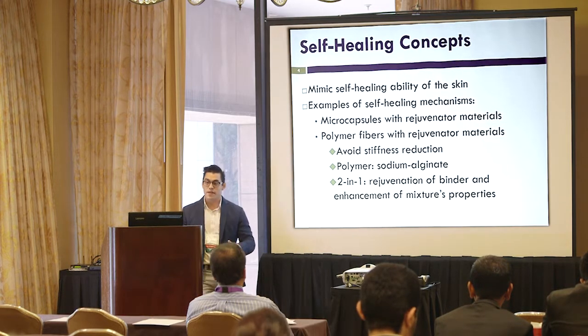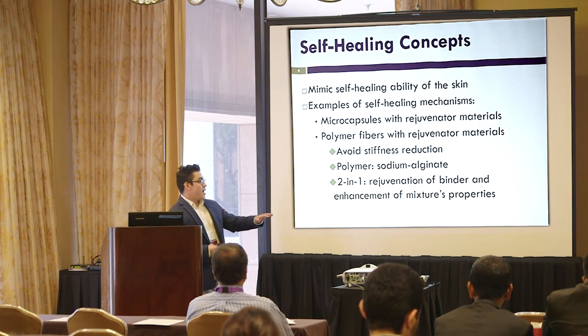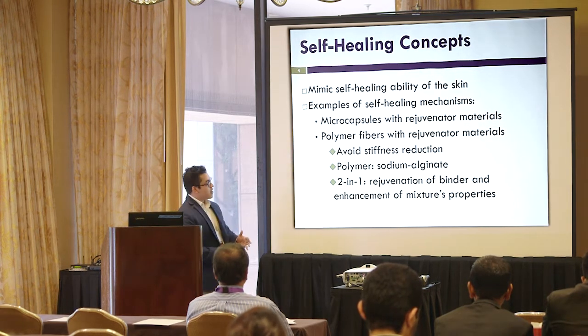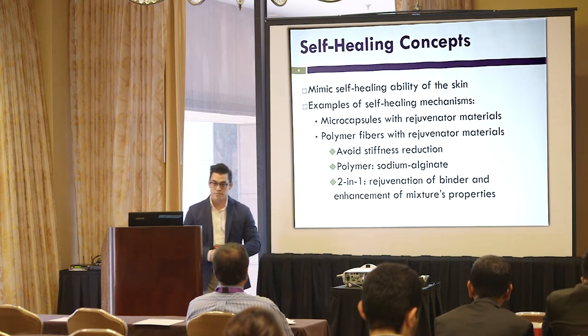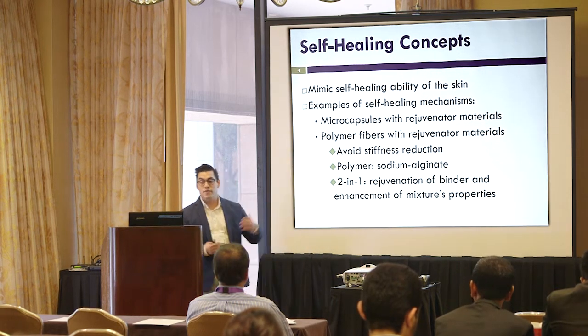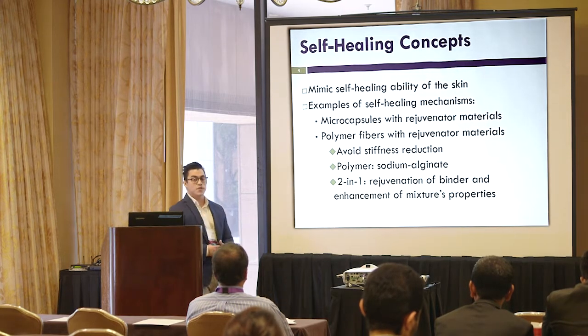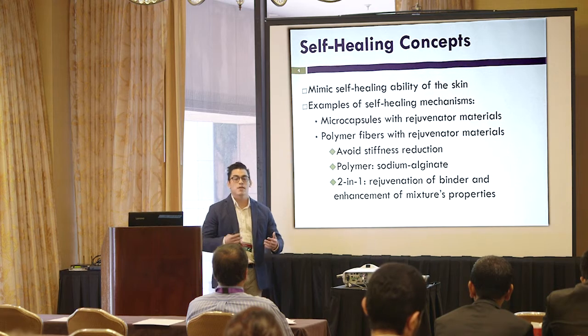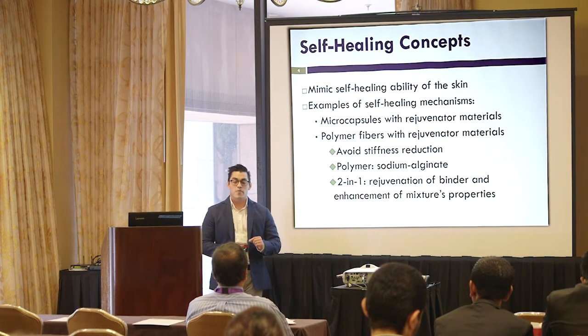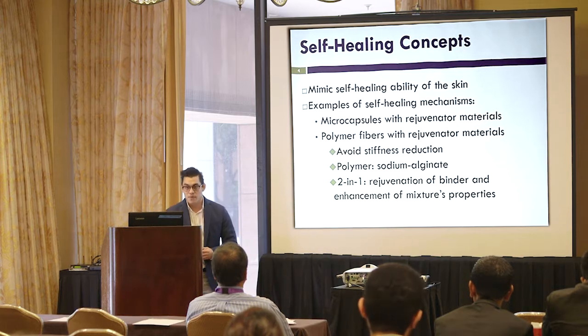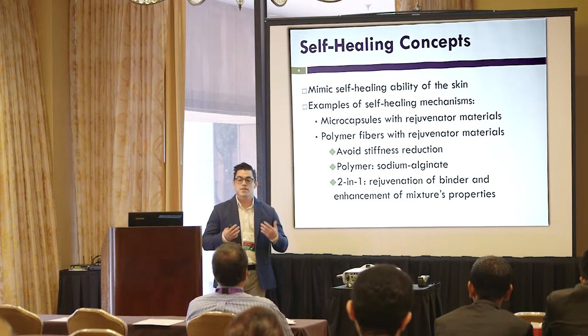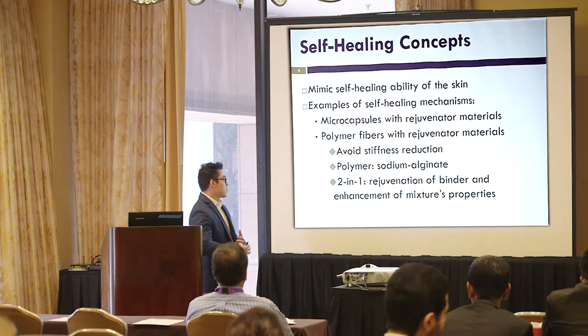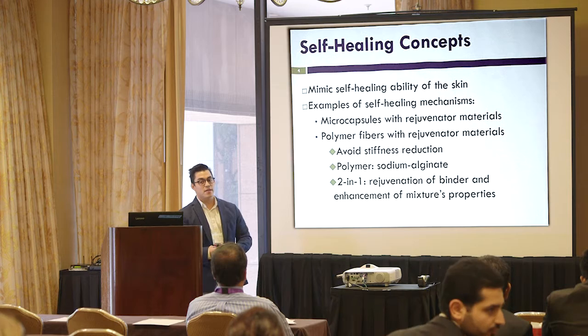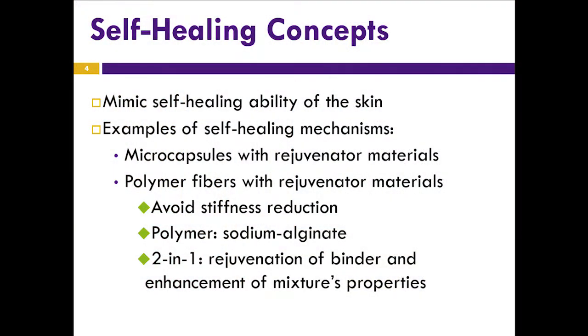I'm going to focus on polymer fibers for this presentation, as we observed that whenever we were adding microcapsules, we were having a stiffness reduction. So we are not going to have this problem with polymer fibers. The polymer that we chose was sodium alginate. We chose this polymer because it is biodegradable. So it's going to give us another way to release the rejuvenator product after some years of service. And basically we're expecting a 2-in-1 product with these polymer fibers. We're expecting some enhancements in the performance of the HMA mixtures, and also we can rejuvenate the binder.